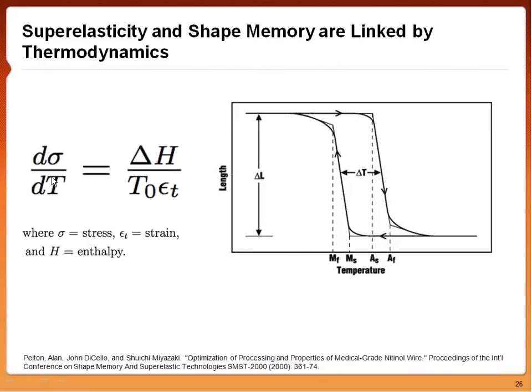And so we have a certain stress rate, which was related to a heat flow out of the system, an initial temperature of the two phases, and a strain rate. You can see too that with the previous curve on this axis, I had a volume fraction of martensite, and I saw the temperature. The curves look the same, and that's because they're linked through the fact that you can induce a phase transformation by applying a pressure or a stress, just like you can induce a phase transformation by applying a temperature.